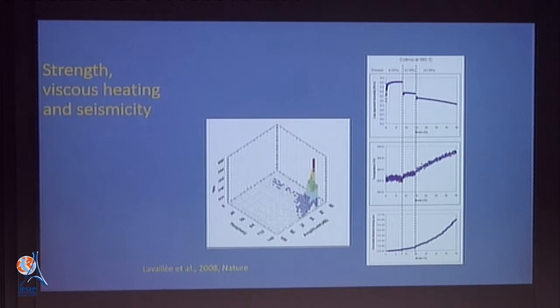These things are seismic, I've said it before, and so our experiments are seismic if we want to take the trouble to measure it. And so we measure it with acoustic emission sensors. And you can look at the statistics of acoustic emissions. If you look at the left-hand side of the diagram, you have the time, and then you have the amplitude in decibels on the right-hand scale, and then you have the number of events or hits, which is showing you how events ramp up to a catastrophic failure, both in terms of amplitude and in terms of the time scale of deformation.